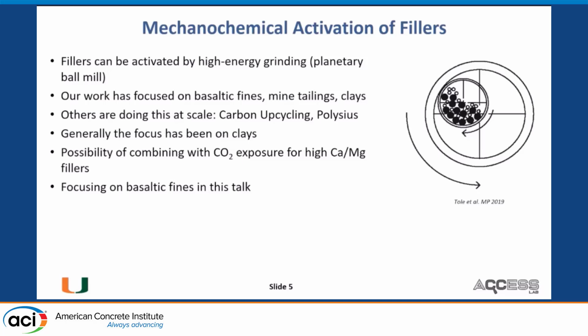So others have looked into CO2. That is, when you have high calcium and magnesium products, during the grinding, you add a little bit of moisture and then you hit this with CO2. I think for certain specific products, this makes a lot of sense. I personally would not do it for fly ash or slag, but for steel slags or recycled cement products, this could be a very useful solution.